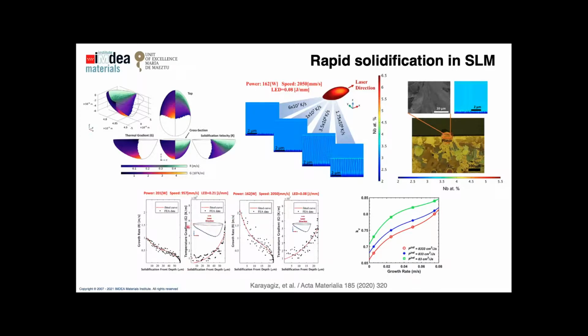So you may very well be in rapid solidification regime at the tail, but for 90% of your melt pool be in non-rapid solidification regime. And that's something that they see in these simulations here, that they actually have a planar front here that restabilizes and microstructure developing at the bottom. So whether or not the transition to planar is quantitative, I mean, there's still some work there, but that's most definitely going in the right direction.